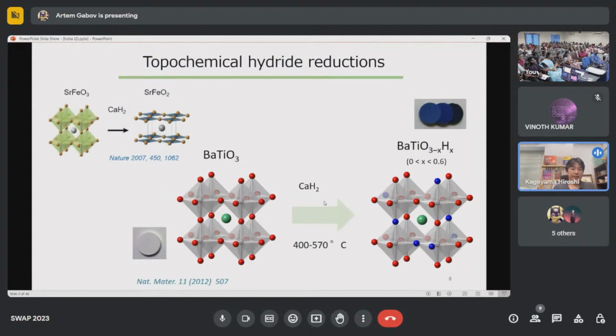Then in the previous example of topochemical reactions of iron perovskite, I showed the structure conversion, but in that case, oxygen is only removed. But in this second example, this barium titanium oxide, in addition to the oxygen removal, hydrogen or hydride ions are inserted into the structure with this calcium hydride reaction. Okay.